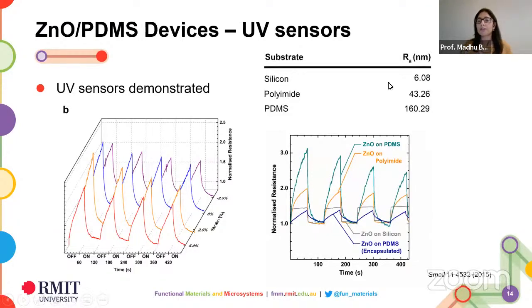So this table here, for instance, shows you the surface roughness which we can get on PDMS. And that's pretty much the same reason why the gas sensors also work at room temperature. It's the surface roughness aspects of it, which lends to better sensing performance. And the other aspect for the gas sensors is also the fact it's a PDMS-based platform. So PDMS is gas permeable, which means there's much more gas interacting with the sensor and you get better sensing performance.